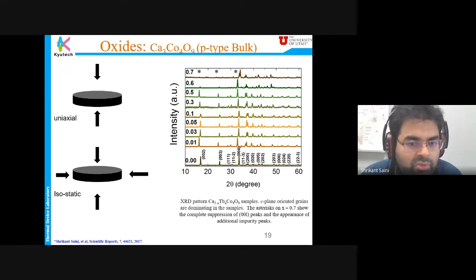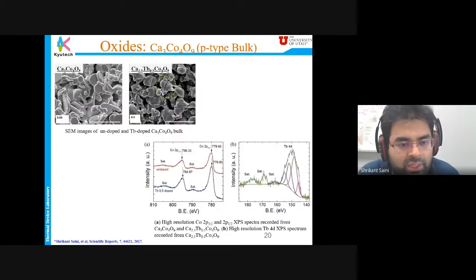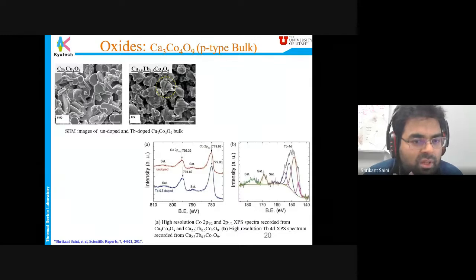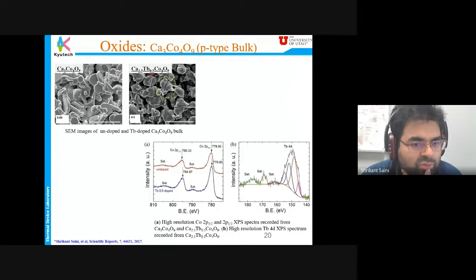So in our case, we found the solubility limit was around 0.5 to 0.6. After that, you see this peak start disappearing. That's where the phase starts changing and a different phase starts happening. So we stop over there and we saw how much response we get from this kind of material. We fabricate these materials and then we see the structure of this material, where we found 0.5 shows the best, and this is the pure material.